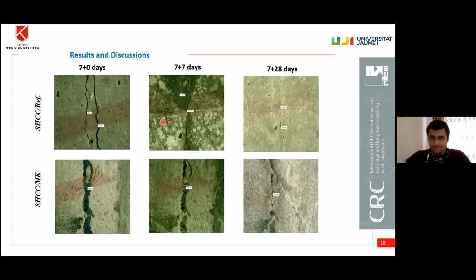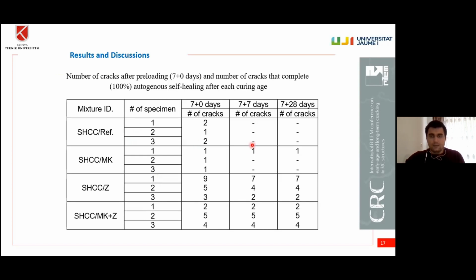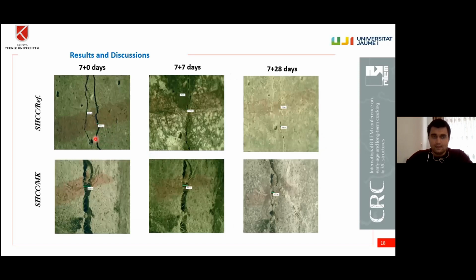We can also see the autogenous self-healed cracks. You can see, for example, that this first image belongs to this specimen. After 7 days and after 28 days, all the multiple microcracks of this binary mineral admixture mixture closed. This was also pronounced for the zeolite only bearing specimens, but we didn't observe so much progress in the metakaolin bearing and reference specimens. You can see the assessments of cracks specimen by specimen. You can see that there are still inadequate self-healing products here for the reference.